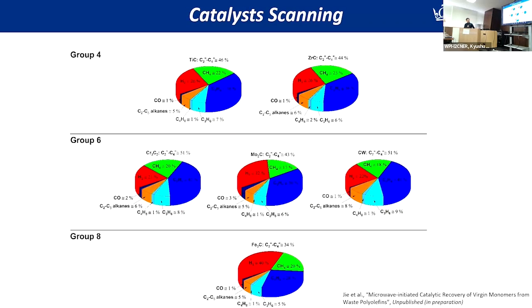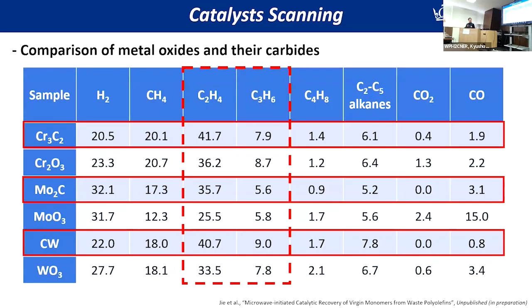Again, for the catalysis scanning, the iron aluminum oxide is superb for targeting carbon hydrogen bond breaking. But recycling to monomer is more challenging. We scanned different types of catalyst, and we found the group 6 carbide materials, including chromium carbide and molybdenum carbide, could serve as very good microwave-responsive catalysts for monomer recycling. Although it's still not perfect yet, and we are still trying to modify the catalyst by using a different structure, we can now recover a yield of 50 to 70% of olefins, including ethylene and propylene, in the gas phase.